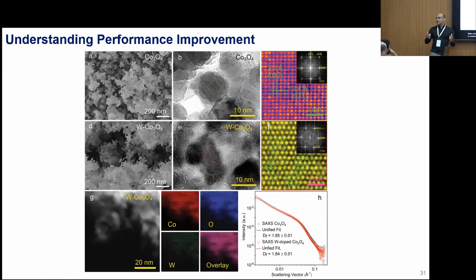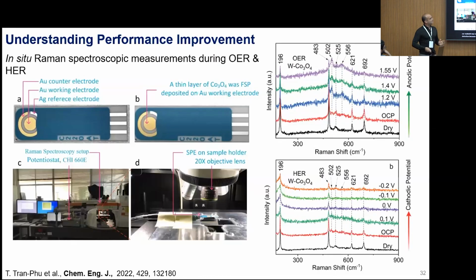Are we changing it? Actually, we characterize our material very well. They are basically identical from a crystal structure, just a bit distorted because of the incorporation of the tungsten. And we performed the in situ study. This is in situ Raman during electrochemistry, OER and HER reaction, and we can see that something is changing in the surface.